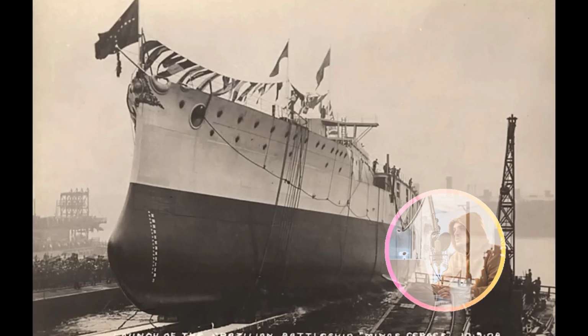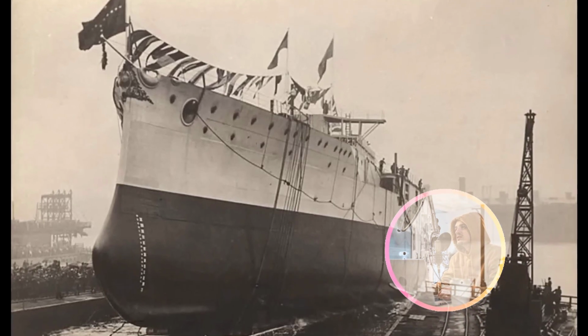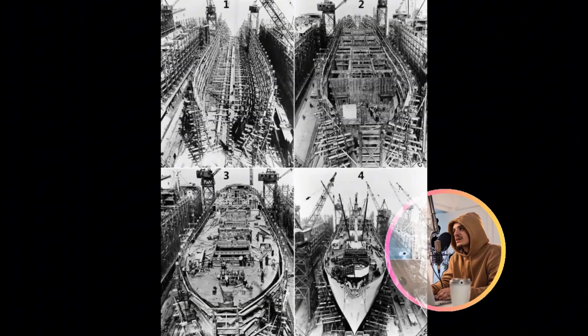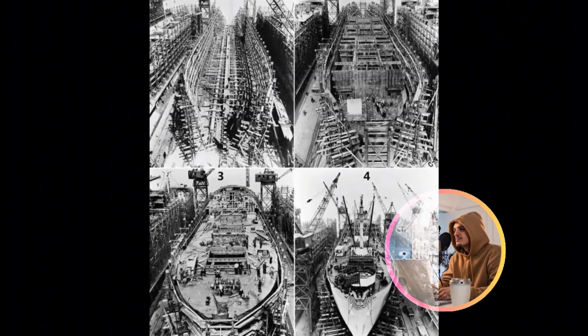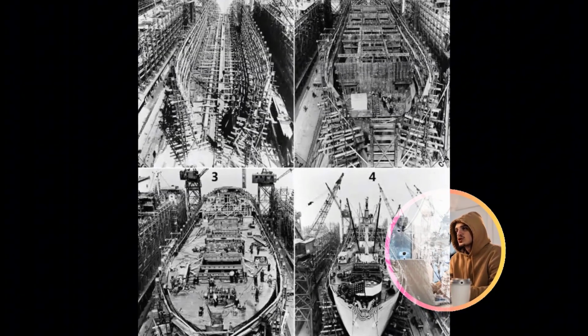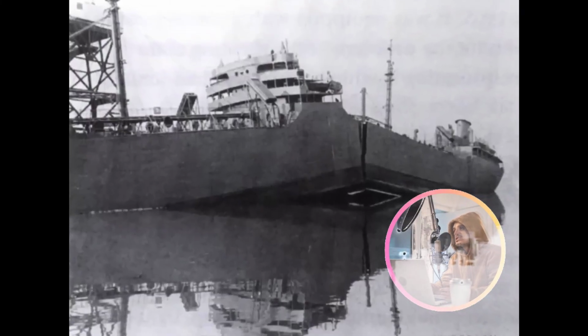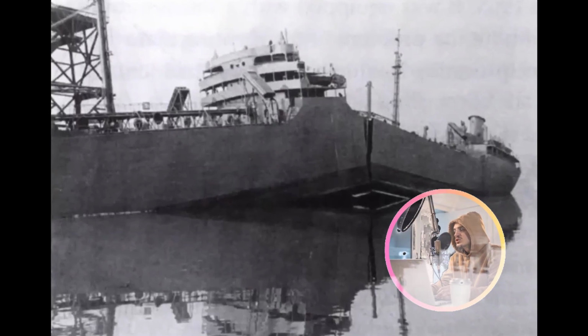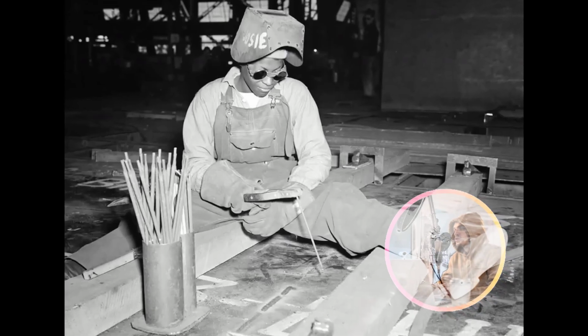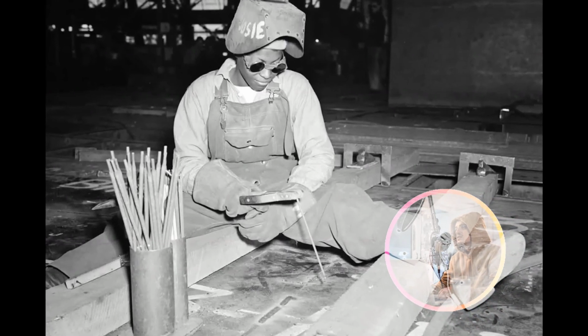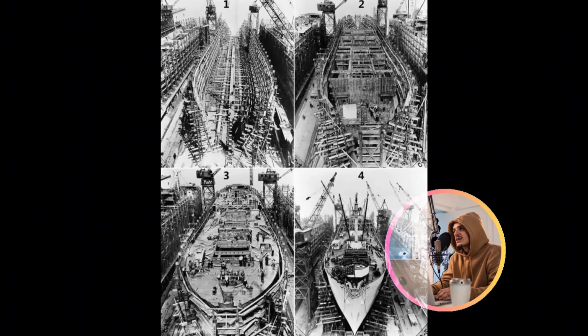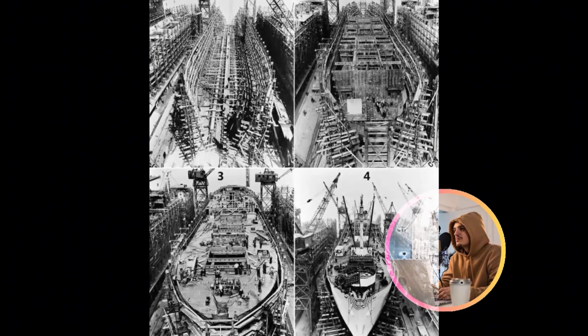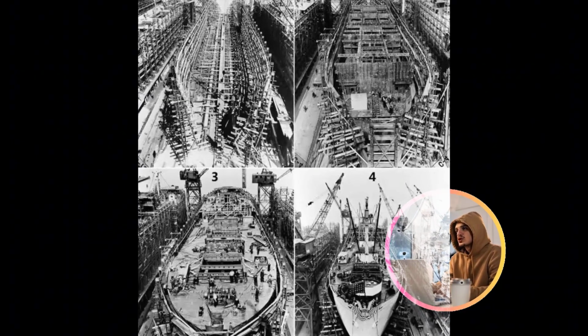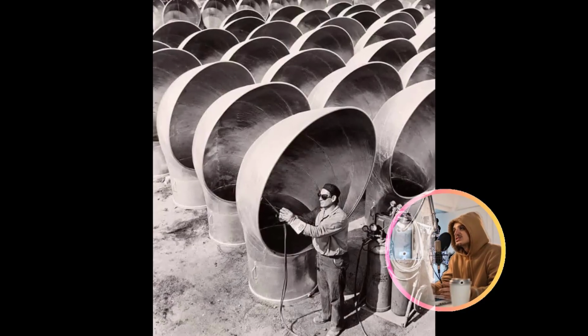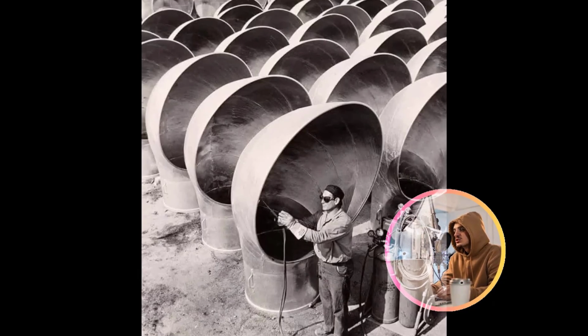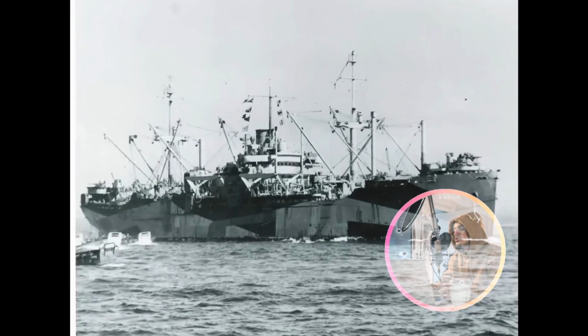These hybrid connection points were not accidental. They provided intentional discontinuities within the structure, serving as critical barriers where a propagating crack, upon encountering a mechanical joint, would effectively lose its destructive energy, thereby potentially halting its advance before it could consume the entire hull. This groundbreaking design philosophy explicitly acknowledged the possibility that cracks might indeed initiate, but crucially, it engineered multiple robust arrest mechanisms to actively prevent their catastrophic propagation. It represented a paradigm shift towards defensive engineering, meticulously planning for potential failure modes rather than operating under the precarious assumption of inherent structural perfection.